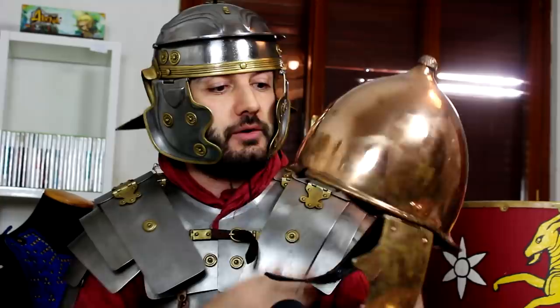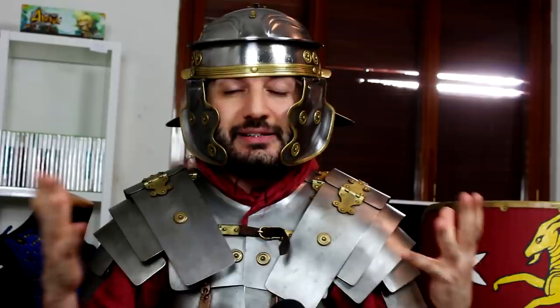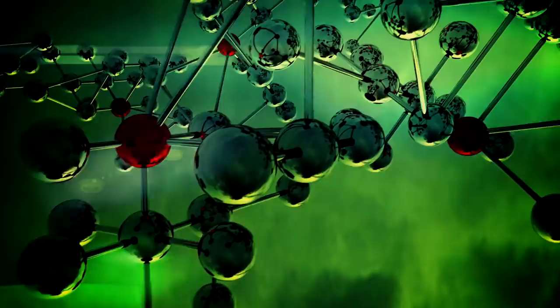What were these chest protectors made of? The traditional answer would be copper alloy. Modern bronze — just like this replica of a Montefortino helmet — is copper plus tin. But in ancient times, whenever we read 'bronze,' it's not always copper and tin. Sometimes zinc was also added, which technically makes it brass from a modern perspective. Other times, neither tin nor zinc was added and you have something in the lines of arsenic bronze. And other times historical bronze is just copper plus a lot of other stuff.